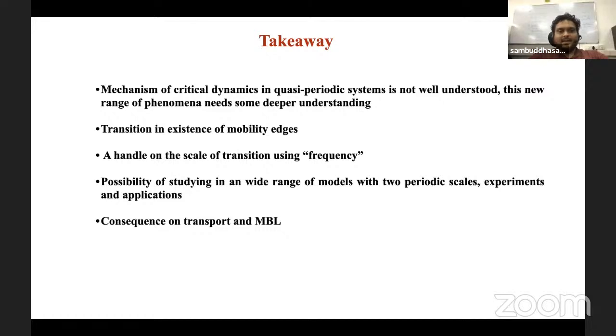And we found a general criterion for the transition in the existence of mobility edge, and it happens in any two periodic scale models. We found that there is a handle on the scale of transition using the frequency, and we proposed the possibility of studying this in a wide range of models and showed a rich range of dynamical behavior. And we think all these findings will have an interesting turn in the study of transport and MBL.